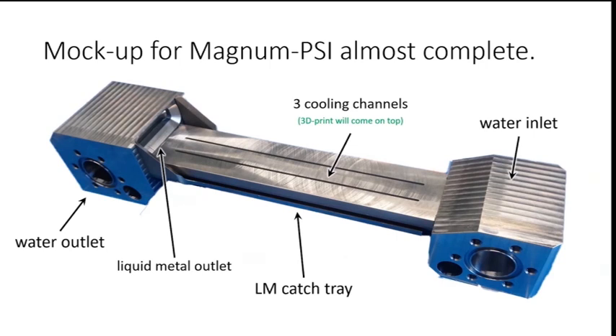You need to know this, and then how much energy does one particle dissipate in the plasma? Does one particle of lithium dissipate, I don't know, 500 or 5 electron volts, right? That already shows you there are some order of magnitude errors here. But nevertheless, if you would have a lithium surface thickness of, let's say, 0.1 millimeter, so 10 to the minus 4 meters, and the lithium radiates very effectively in these conditions, so let's say it dissipates about 500 electron volts per lithium particle, you can withstand a disruption of, let's say, 1, 2, 3, 400 megajoules per square meter.